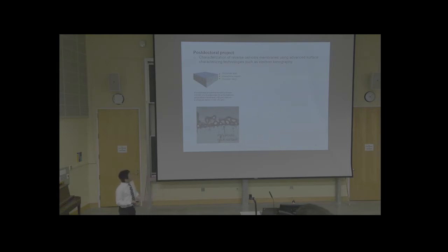So during my postdoc, I learned electron tomography. I used to teach the videos after I did the reconstruction. Basically, we delaminated this film and put it on a TEM grid and then tilted it in the TEM from 70 degrees to minus 70 degrees. Then we get different image sections, and we use different algorithms to reconstruct in 3D. This is the 3D model I constructed.